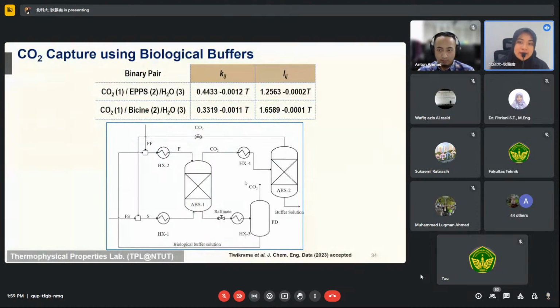So the same here, we need to calculate the binary interaction parameter, and you can optimize the, let's say, some absorber here. You can use the CO2, this is fresh feed, fresh solvent, and then here you can use the buffer, and the other fresh feed is CO2. So CO2 will go out, and they will go to the absorber too, because maybe some CO2 will remain from the outlet of absorber one, then they will go to the second one. So seldom in industry just use one column. They mostly use 2 columns or even 3 columns to totally purify their air or gas mixtures. It's impossible we just use once. Of course, we use 3 or 2 in sequence. Then in here we can try to recycle, yeah, even buffer solution here can recycle again to here. So that's why we need this interaction parameter.